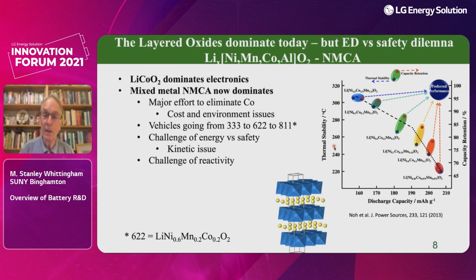But the thermal stability, we hope we never get to these temperatures, but the thermal stability is a direct measure of the reactivity of these materials with the electrolyte. So they give problems with capacity retention. So our challenge is really to get in this top corner. We want the greatest stability and the highest capacity we can get.